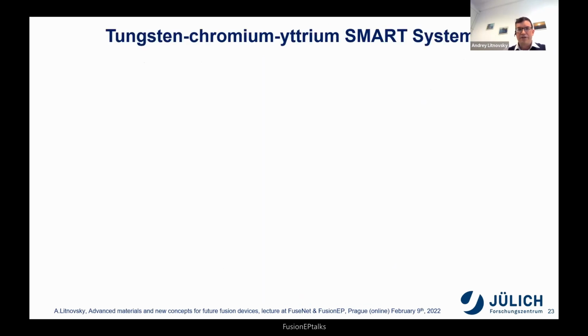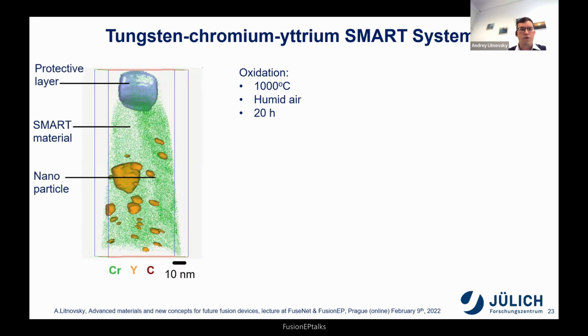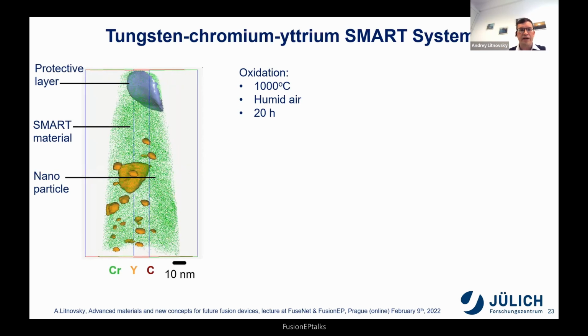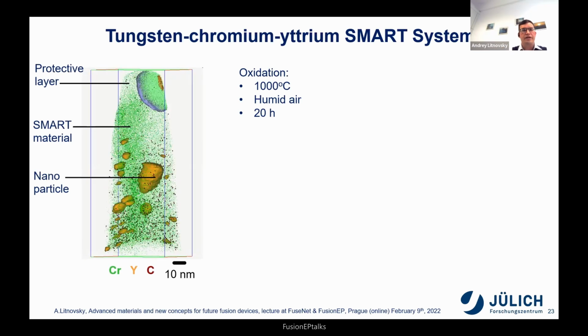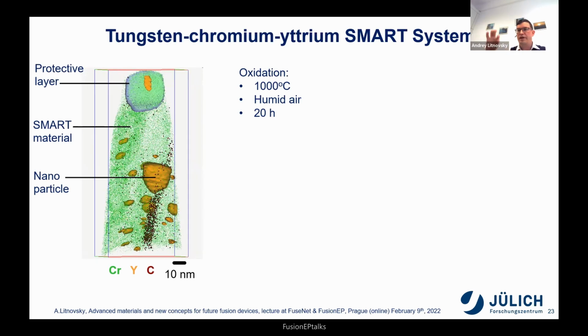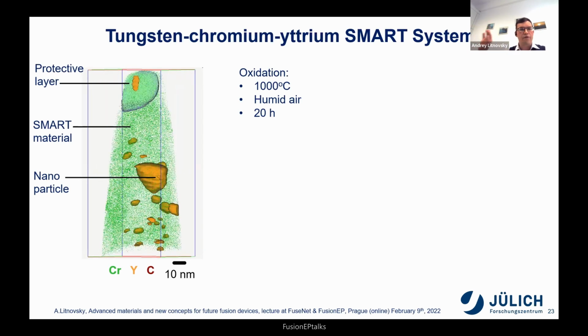As I said, these materials, one of the most advanced, containing tungsten, chromium, and yttrium, are in fact quite scenic. To see how they look, we have the results of a very short, so to say, oxidation for 20 hours in humid air at 1000 degrees C. And these are the results of the so-called atom probe tomography. This is very high-end surface technology, which basically sucks the sample and reproduces it, analyzing all the elements.